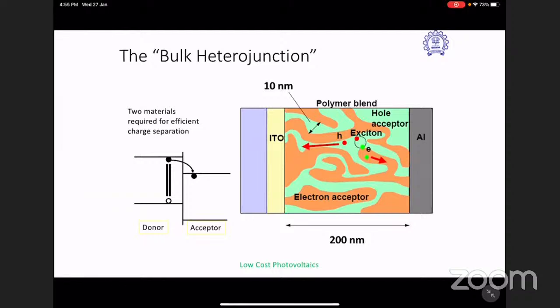So what is basically the energy difference between the top of the donor and the top of the acceptor? That energy offset is going to be one of the important parameters to understand what kind of voltage losses we'll have, because we shine the photon of the energy of the donor band gap, but we cannot get the electron and hole coming out from the solar cell, from the ITO contact and aluminum contact, with the energy more than the work function of these electrodes. So we are going to reduce the energy offset between the LUMO or the conduction band.